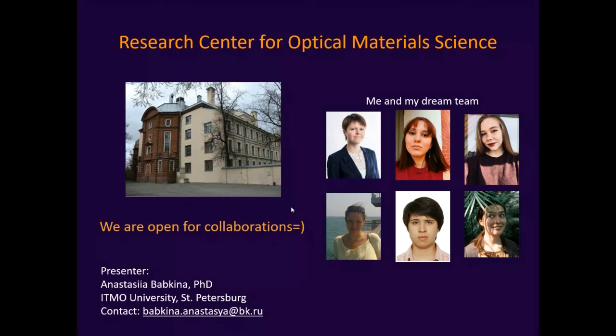Inside of the glass, we can't do that. Because the growing of crystals inside of the glass is a diffusive process, we are working with the oversaturated solid solution inside of the glass, and we induce diffusion by heat treatment. That's why we can't grow a single crystal. There will also be a lot of crystals inside of it, and they will be disoriented relative to each other.